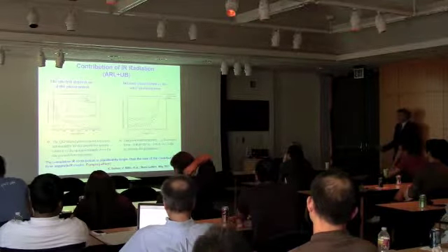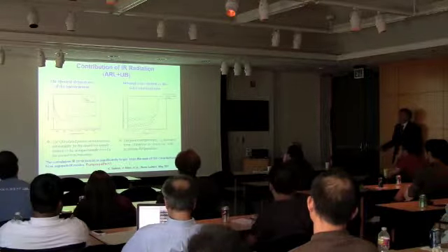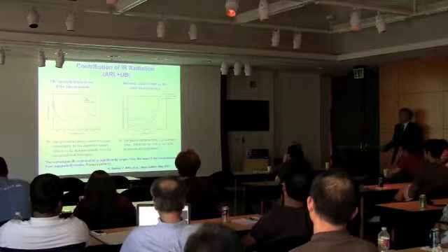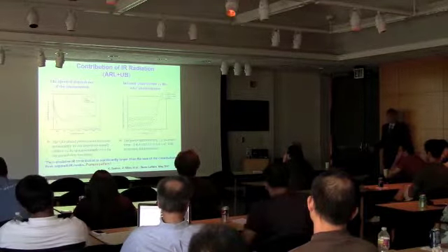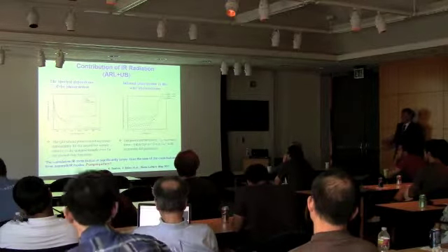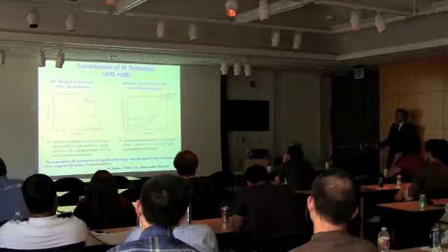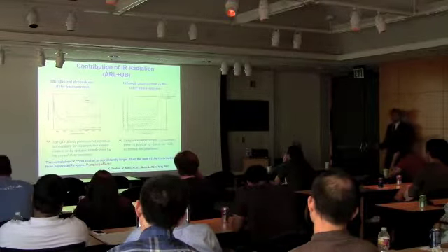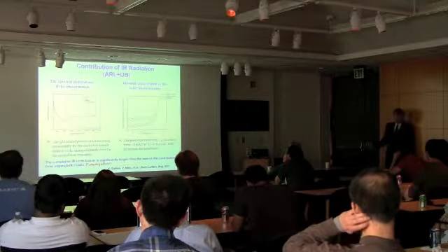And as you see, we have additional current that depends on the doping. And this additional current, we measured, is up to 9 milliamps per centimeter squared. In reality, we did not have 9 added, because you still have some recombination as well. Here it is, of course, shown, as Anna did, that by introducing quantum dots we introduce additional harvesting in the spectrum, and this is just the measured result, the contribution to the output.